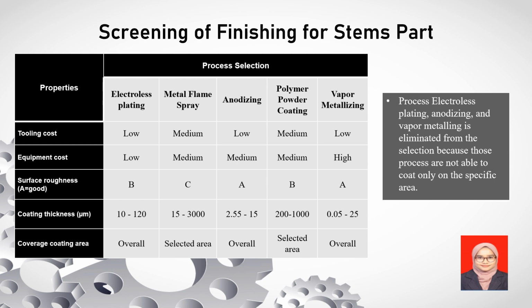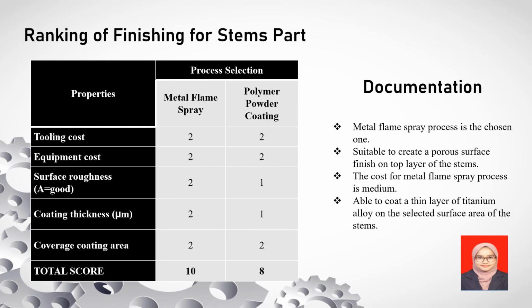Electroless plating, anodizing, and vapor metallizing are eliminated from the selection because those processes are not able to coat only on the specific area. The chosen process is metal flame spray. It is because this process is suitable to create a porous surface finish on the top layer of the stems. The cost for metal flame spray is also medium. It is able to coat a thin layer of titanium alloy on the selected surface area of the stems.